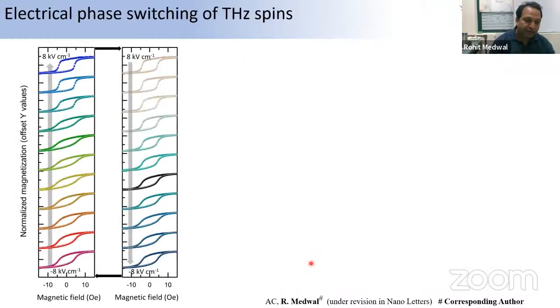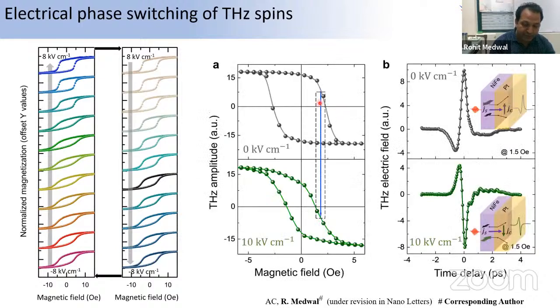Now what we did, we apply the voltage and we see the MH loop. And we can clearly see that we can tune the hysteresis. You can see the shape of the hysteresis tuning as a function of the applied magnetic field. And we utilize this, we sit on this field and we measure the terahertz photon. The moment I change the voltage, I can go from the positive to this negative field, and I can reverse the phase of the terahertz photon just by applying the voltage.